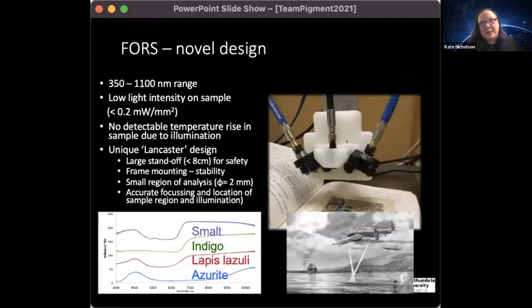Now, while we liked that, we decided we wanted one that was going to be just as good, but we didn't have to hold it. We could put it on the same frame as our Raman instrument. And we used the Lancaster bomber design, where the beams cross, you're at the right height to take the measurement. So two light sources coming in from either side, move the height, and where the beams cross, you're taking the measurement through the fibre in the middle. This allows us to have quite a large offset from the page, so we're definitely not touching. And we can get some nice results. It also allows quite a low power to be put on the page, but you do have to do this in the dark, like all spectroscopists.